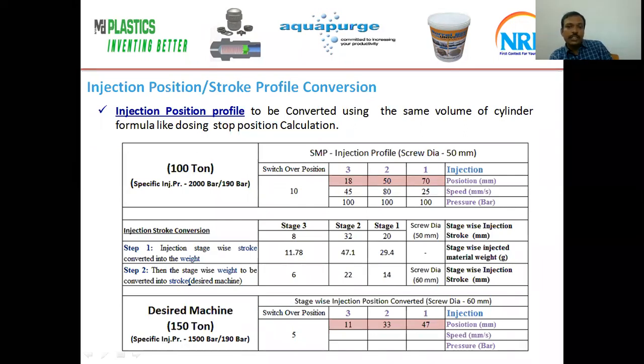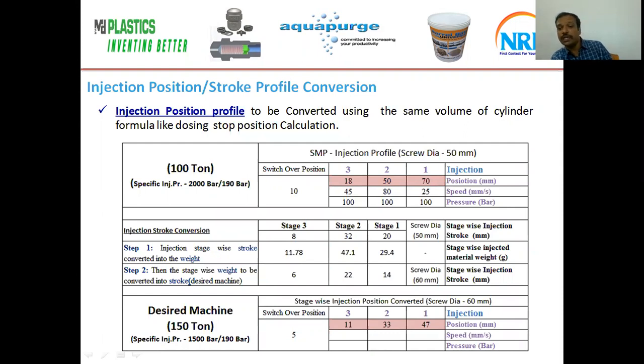Injection position and stroke profile conversions. The injection profile is converted using the same volume of cylinder formula as the dosing stop. See, the 100 ton has a specific injection pressure of 2000 bar and hydraulic pressure of 190 bar. So we have that injection profile: position 70, 50, 18, speed 25, 80, 45 and pressure 100, 100, 100. Now I am going to convert this profile to the next desired machine, the 150 ton.